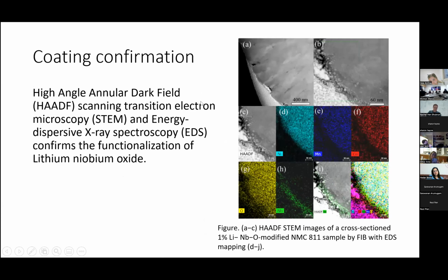This is confirmed by high-angle annular dark-field scanning transmission electron microscopy and EDS for elemental mapping, which showed the surface coating as well as substitution of niobium in the NMC. In figure H especially, you can see the surface coating as well as substitution inside the NMC particles. The rest, D, E, and F, are the elemental mapping of nickel, manganese, and cobalt. Figures A and B are the cross-sectional images of the NMC particle, in which you are able to see the coating as well as a small percentage of substitution of niobium inside the NMC.